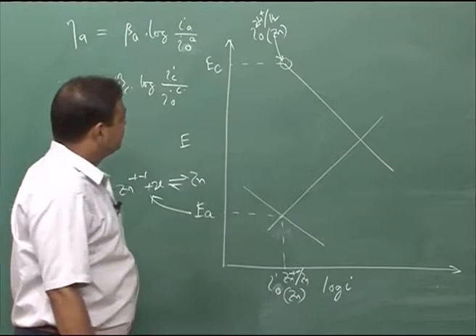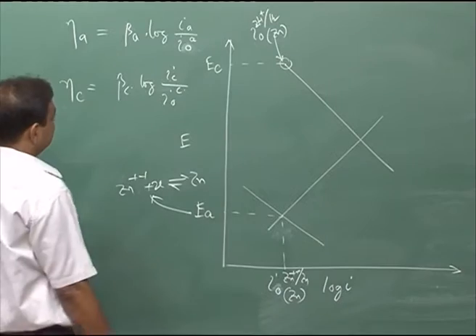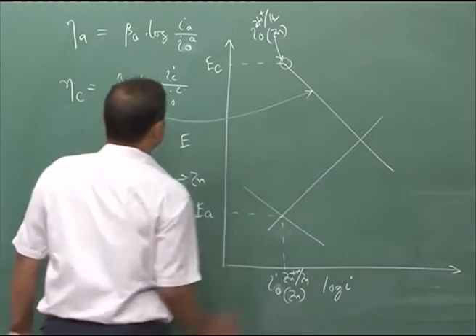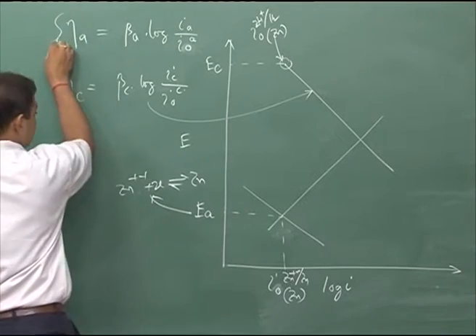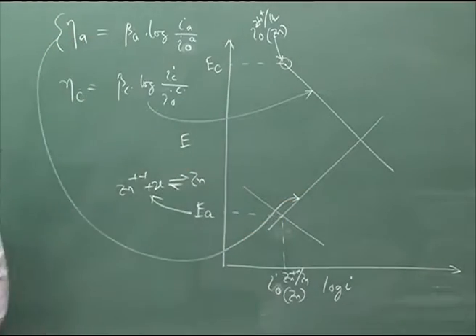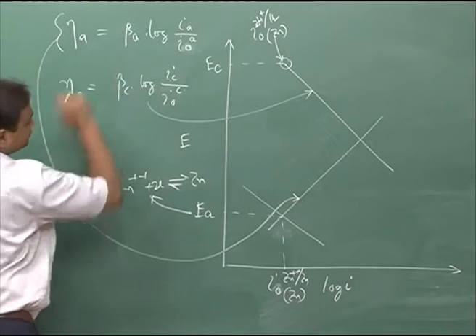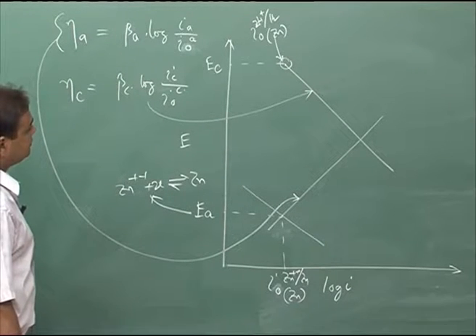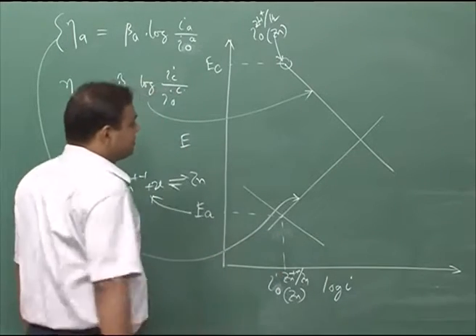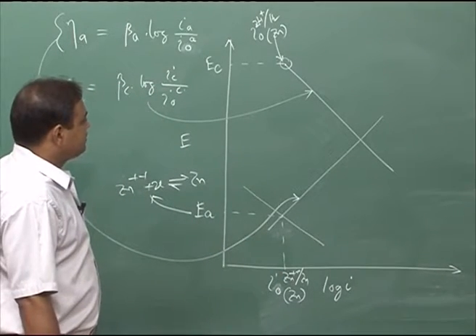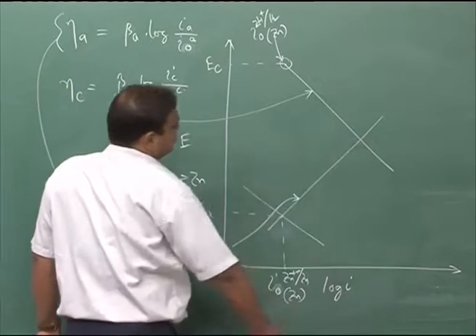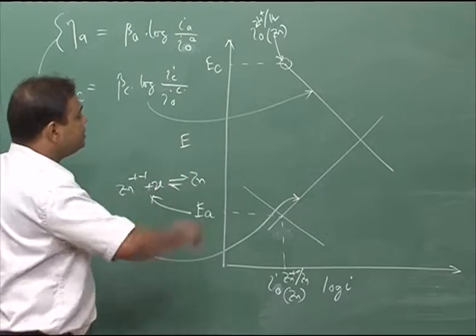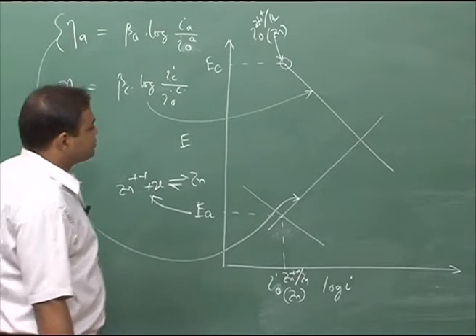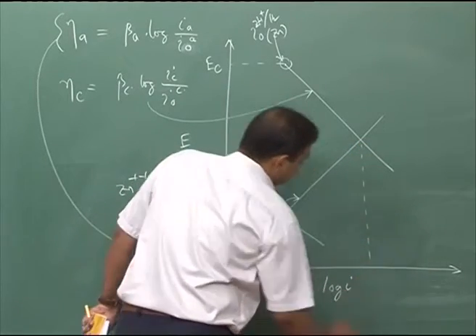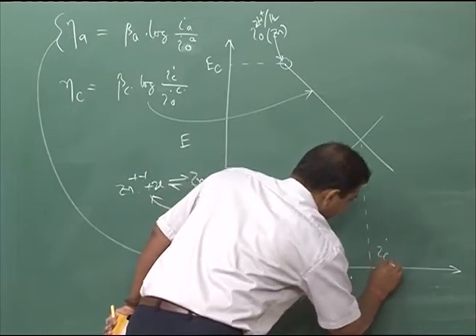This is the cathodic polarization, and this indicates this, and this one indicates this. So, the two lines are drawn from this concept of Tafel equation. If we have zinc dipped in HCl, the potential of the zinc will be at this point, which is the corrosion potential, because it will reach a new equilibrium state, and the corrosion would happen as per this current density, which is I corr.